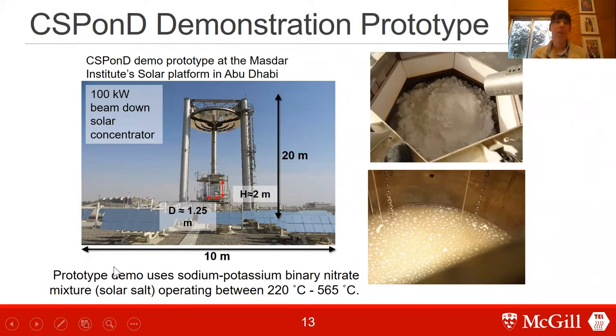And so the salt that we used is solar salt, and it operates between 220 degrees Celsius and 565 degrees Celsius. And so we use this prototype first. So this was the very first demonstration of a direct absorption, direct volumetric absorption solar receiver. And we used it to carry out several experiments to test the performance of the receiver.